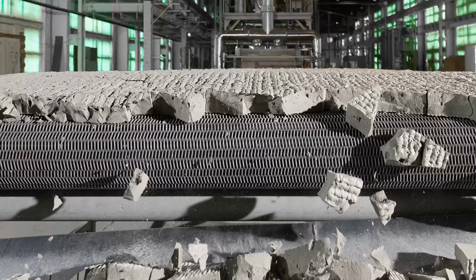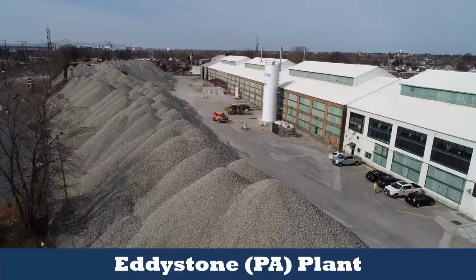All right, so product is still certainly warm here at this stage. It's not completely cooled off, but it's cool enough to have induced that thermal cracking that's necessary to have pieces of product. All right, so at this point, it goes onto the conveyor and it goes outside. We do isolate product until it's been quality control tested, but once it is QC tested, it goes into the larger product stockpile. So this is an aerial photo of our plant in Pennsylvania.